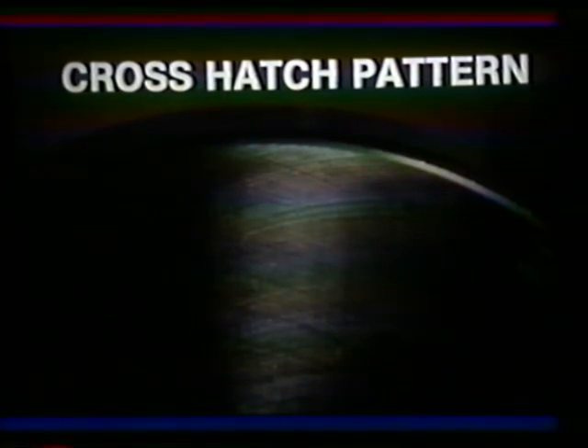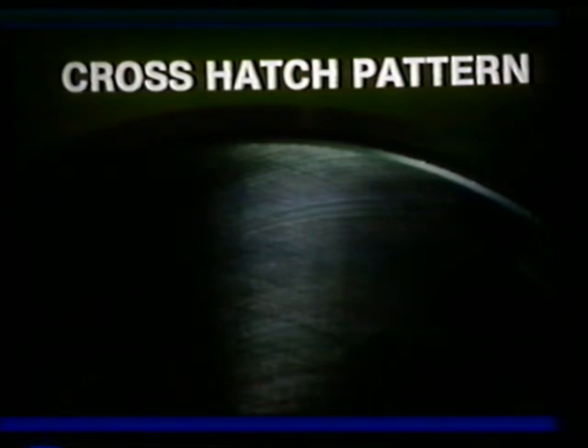After heat treatment, liners are honed. This results in a crosshatch pattern which aids in oil retention. Since our liners are heat treated prior to honing, this crosshatching will be present for millions of cycles, improving reusability. The last step in manufacturing our liners is the process of roll burnishing. This cold working hardens the flange area to increase both its strength and fatigue life. All Caterpillar liners are roll burnished.